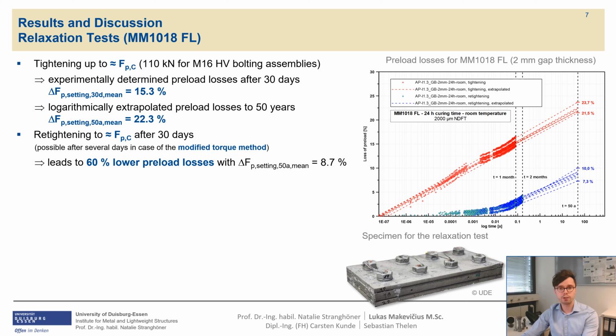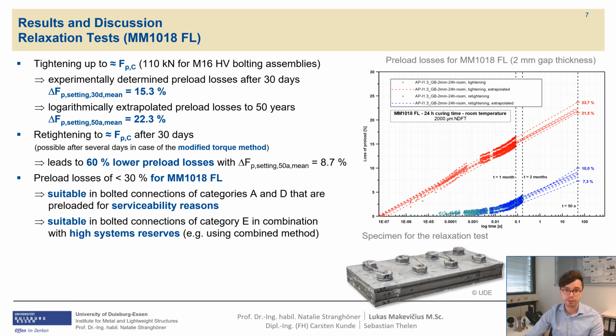So, the first investigations into preload losses of Duroplastic gap filling material MM1018FL, the liquid version, showed that the preload losses due to setting effects and creep remain within 30% and indicate its potential for the use in preloaded bolted connections. While the suitability in bolted connections of categories A and D that are preloaded for serviceability reasons is quite obvious, it also might be possible to use the MM1018FL in preloaded tension connections of category E. However, this would require high system reserves that might be achieved, for example, by using the combined method according to EN 1090 Part 2.